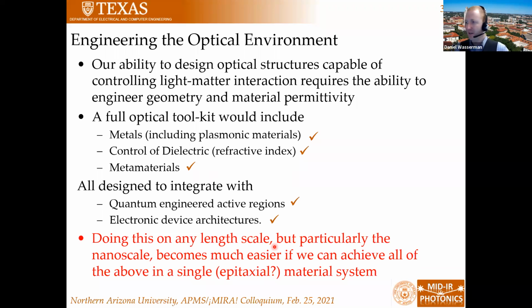grown epitaxially. And I never said it explicitly, but you may have noticed that it's actually all in the same material family. All of these materials and devices are grown in the so-called 6.1 material family, namely the 6.1 angstrom lattice constant, which is basically gallium antimonide, indium arsenide, and their alloys, right? So that means that we have this sort of material system where we can engineer the optical properties of our materials, but also the electronic properties of our materials. And this is exactly what we wanted to be able to make optoelectronic devices for the mid-infrared.